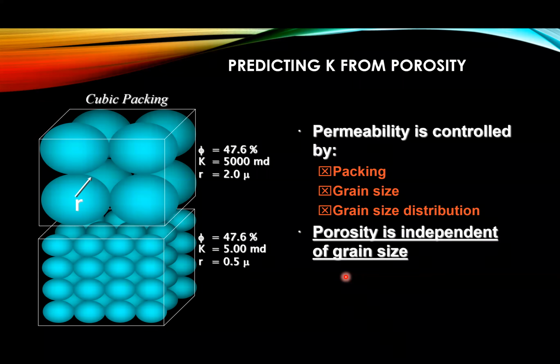I'm just going to show you a little bit of an idea on pore size and permeability. Consider this cubic packing here, right? The top one is a cubic packing, the bottom one is a cubic packing, with bigger grain size and smaller grain size. If you look at the porosity, phi indicating porosity, it is 47.6% here and also 47.6%. So that's the same porosity, and the total pore volume is the same. But if you look at the permeability, K, you see there's a significant difference. With this diagram, I think you get a fairly good idea of how permeability changes with grain size, or pore size, not necessarily with the total pore volume. So you have the same pore volume, but your permeability varies quite significantly.